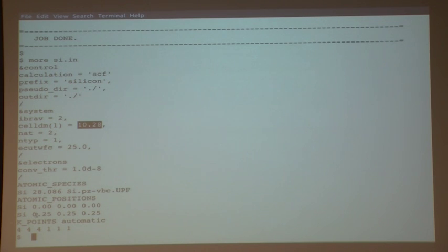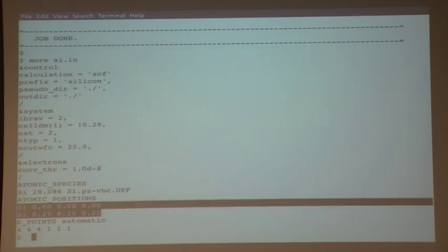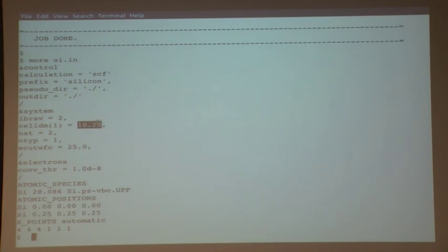So if you look here, these are given essentially in crystal coordinates. So if you expand the parameter, they move with that. So you don't need to worry about that. The important thing is to change this number. Okay. So the idea is to do exactly the same thing that we did for silicon, but changing this lattice parameter, do, I don't know, 10, 20 calculations, trying to stay around the experimental lattice constant so that you don't look at something irrelevant, and then trying to plot the result.